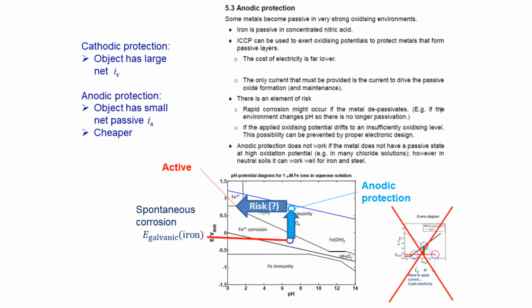The second advantage of the anodic protection system is that because our protected pipeline is forced to become an anode, there is no possibility of the nearby pipelines being affected by stray current. They can't be made into an anode. I guess there's a tiny possibility they might be made into a forced cathode, but that would be protective for them, so that's not going to be a problem. So the anodic protection, where possible, is not going to cause stray current corrosion problems in the same way, so it can be safer to apply in a complex underground environment.